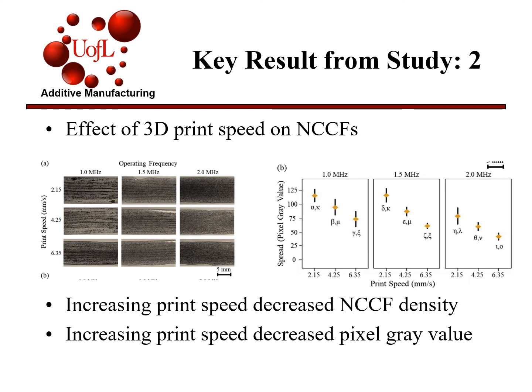The good news is that the ultrasound frequency does increase its density, so we can somewhat counteract the effects of an increased print speed, but there is a limit, because as your ultrasound frequencies increase, you also introduce more thermal energy into the system. So there is an upper limit to how much energy we can actually put in, and how much of these print speed effects of lowering the density we can actually counteract.